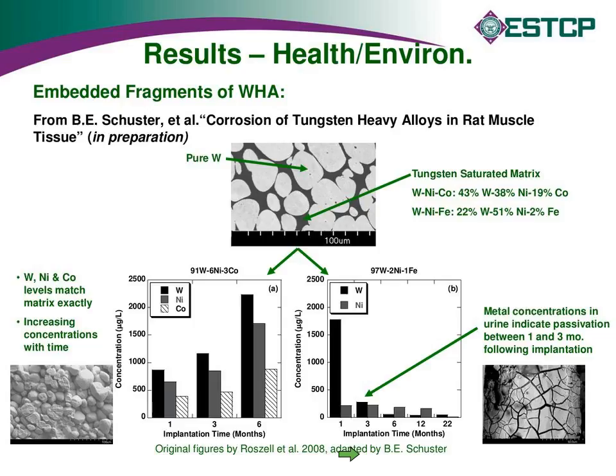And so it's pretty clear from that, plus some subsequent SEM analysis of the corroded pellets, that it was definitely coming from the matrix only. In contrast, the tungsten nickel iron alloy had initially elevated levels of tungsten and nickel, and then that dropped off steadily with time. And if we examine those pellets that were recovered from these tests in the electron microscope, you see the formation of this thick iron-based oxide that shuts down the operation of the galvanic cell. And so it limits the bioavailability of both tungsten and nickel.